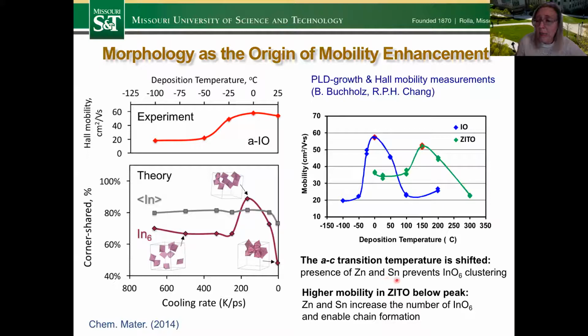But again, looking at the structure, we can see that the presence of zinc and tin prevents clustering that we've seen in indium oxide, and nucleation, and that's why we have a shift in the temperature and a shift in amorphization as well.